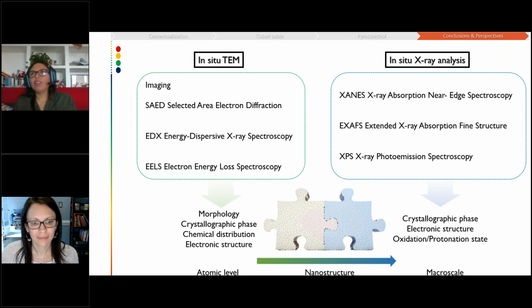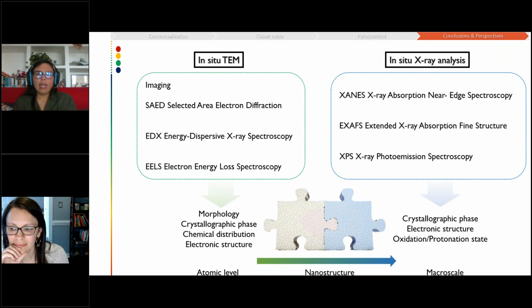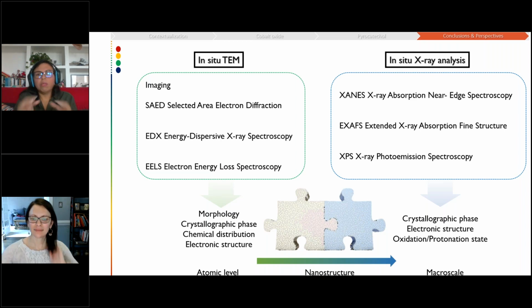No, unfortunately not. Thank you for this question, because it's definitely another thing to add to the list of wishes that we would like to have. I know that, for example, Arnaud de Mortier has started doing some steps towards that, recovering the electrolyte from reactions. We should definitely do that. We would need really sensitive mass spectrometry to be able to determine it, because the amount, if we recover the samples from our in situ setup, will be very small compared to a 3-electrode cell. But that is something we would like to do, to prove that the metals are not leaching away into the solution. And as Arnaud has done, it's not that difficult to just recover your electrolyte and then test it.